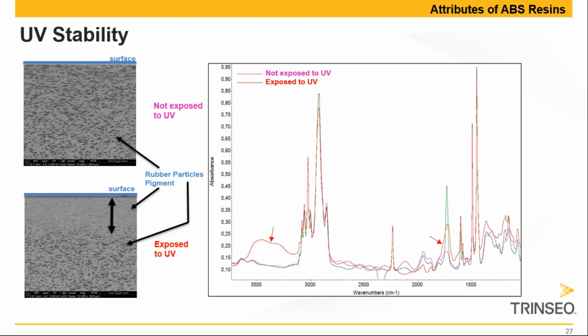So not only are you causing loss in mechanical properties because of embrittlement of the outer layer of your part, but you're also causing some yellow bodies during this cross-linking process of the rubber, which causes coloration. If you look very carefully, you will still see some black dots in this upper layer where the rubber particles are faint. These are the pigments that we use to color the parts.